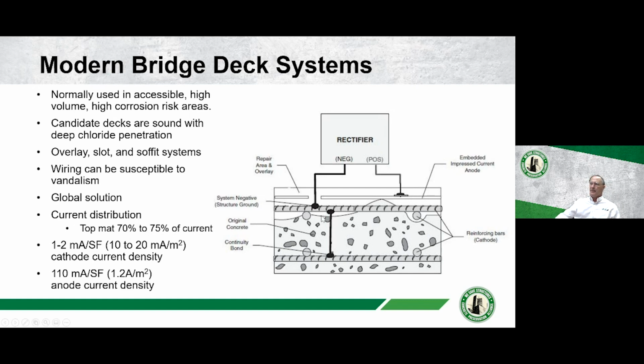And if you have a surface applied anode or an overlay, the steel that's closest to the anode is going to get a large proportion of the current. So you have to factor that in. You may need to put in a little higher current for the system, just so that the bottom steel can get some cathodic protection.